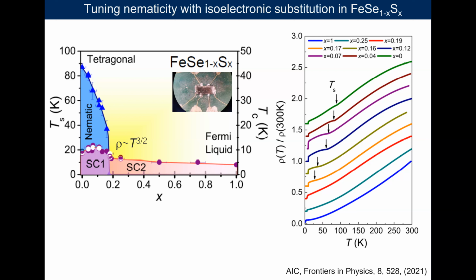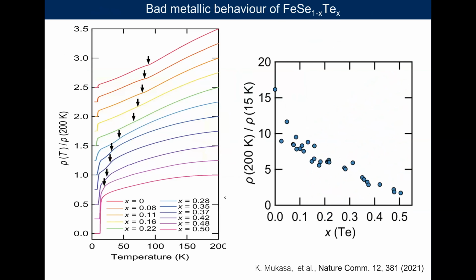These are the resistivity curves. We can see that they are quite nicely evolving from kind of bad metal-like behavior to eventually a Fermi liquid behavior for the end compounds in iron sulfur. If we look at the tellurium end, as I mentioned before, the system is somehow different in how the electronic behavior is, but also in resistivity.